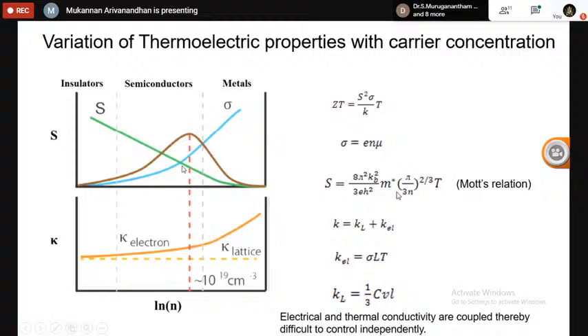So these are all the fundamental relations: the thermoelectric parameters, how they change with respect to the carrier concentration of a material. You can classify the material based on the carrier concentration as insulator, semiconductor, and metal. For an insulator, you have a very poor carrier density, so the electrical conductivity is very low, while the Seebeck coefficient is quite high. Whereas in the metallic material, the carrier densities are higher, so the electrical conductivity is higher. You can see the electronic part of thermal conductivity also follows the same trend as the electrical conductivity according to the Wiedemann-Franz law, right? Then this is the optimum range of dopant concentration in the semiconductor. This kind of doping concentration is quite promising for realizing high performance.